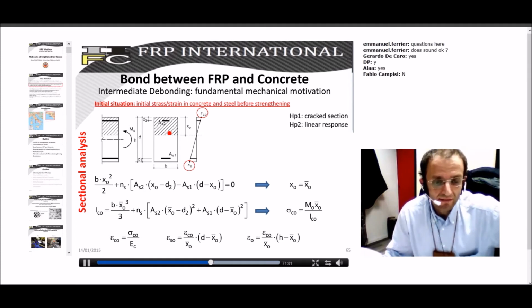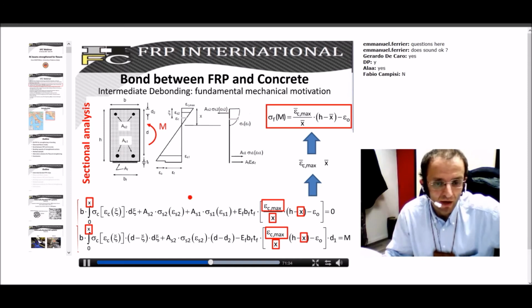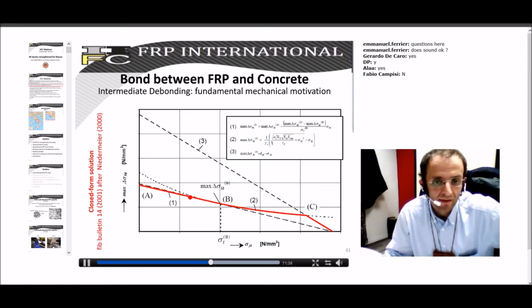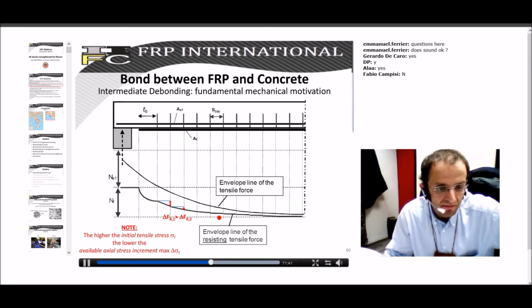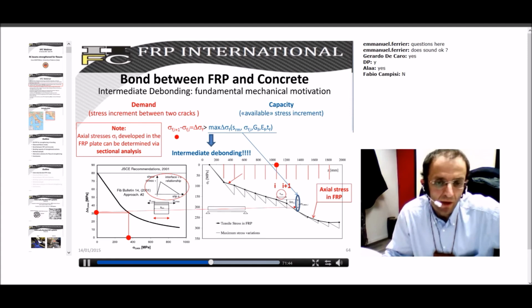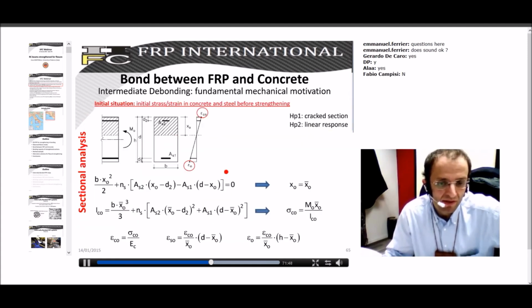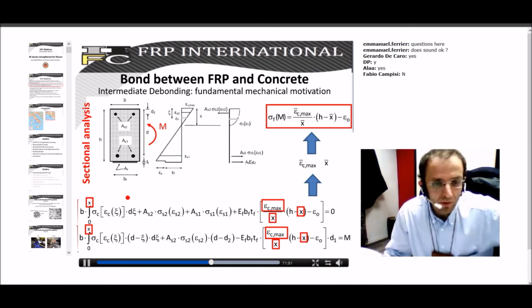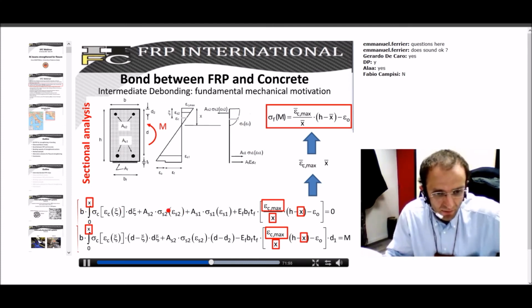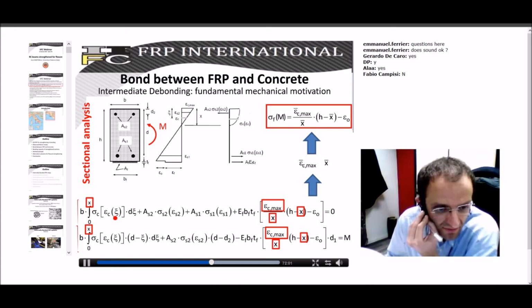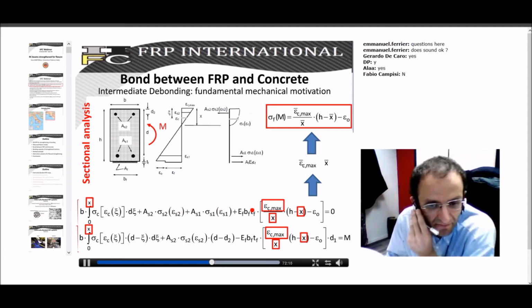So now, to evaluate the sigma in a certain section, we are, for instance, interested in evaluating sigma f in the fiber in this section. How can we do it? Well, we have evaluated the initial state of stress before strengthening. Then, after strengthening, we can write two equilibrium equations: equilibrium of forces and of moments, of rotation. You see here, this is the resulting force for the compressed concrete. This is the resulting force for steel, where sigma depends on epsilon s. It can be in the elastic field or in the post-elastic plastic field. This is the contribution of the fibers, because the fiber has this axial strain.